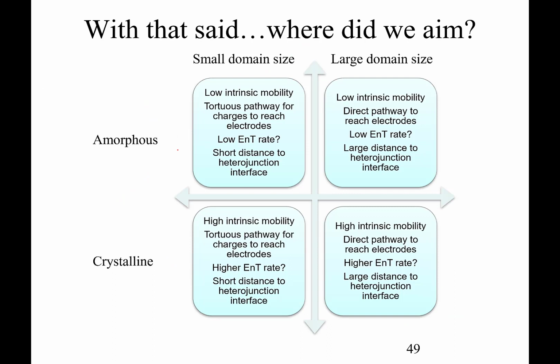So before we started all this, we also thought about we don't want a large domain size. Because if we have a large domain size, we can't get our excited state to reach the interface, and so this would be bad for us. We don't always want a small domain size either. If we have all these very small features in our material, it's very difficult to get the electrons out. It's a very tortuous pathway for those electrons to get out from the device. So it actually slows down the device and reduces the efficiency. So we don't want a small domain size either.